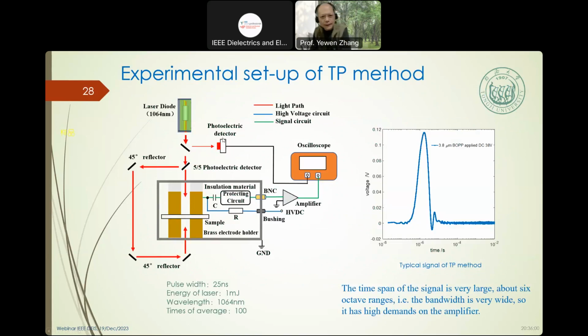So this is an experiment setup for the TP method. This is a laser, for example a laser diode, also an infrared laser. The pulse is about 25 nanoseconds. The energy is small. For the PWP, the energy is usually 5 millijoules to 700 millijoules, but for this one the energy is much smaller. But we average about 100 times. We heat the sample from one side, and there is also voltage applied on the sample. We use an amplifier.